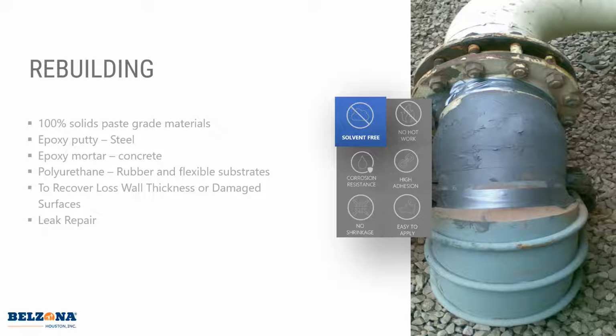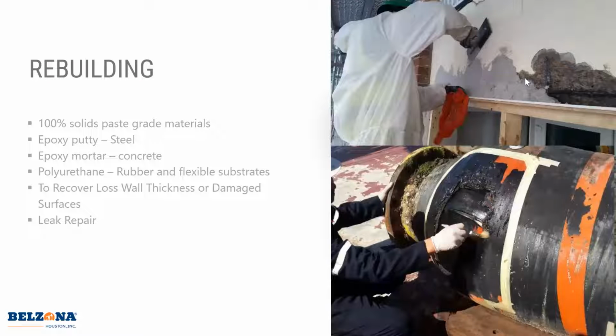And once they cure, they're hard. They're almost like steel at that point, very abrasion resistant, corrosion resistant, and really high adhesion. So you're talking 3,000 to 5,000 PSI. These are built to not come off, built to withstand extreme conditions, extreme chemicals, pressures, and temperatures. Besides our epoxy putties and rebuild materials for steel, we also have materials that can repair concrete, like you're seeing in this upper picture, and rebuilding materials for rubber as well.